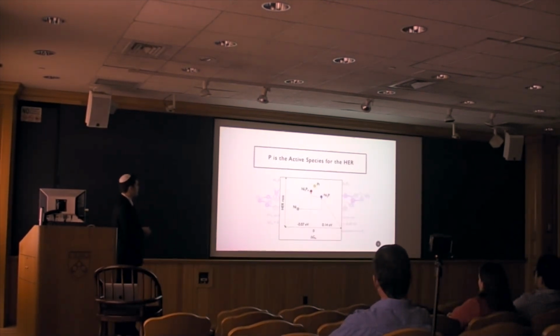And so from here you can see, here's the plot I showed originally a while ago, that as you start from nickel, which binds too strongly, if you alloy with phosphorus to get nickel 2P, then you will get binding energies up here on the volcano. So you've gone closer to the top, which means your activity is increased. Then for nickel 5P4, you're even closer to the top and getting closer to platinum. And so this can explain why nickel 2P is not as good as nickel 5P4, which is almost as good as platinum. It's because of where they fall in this volcano plot.